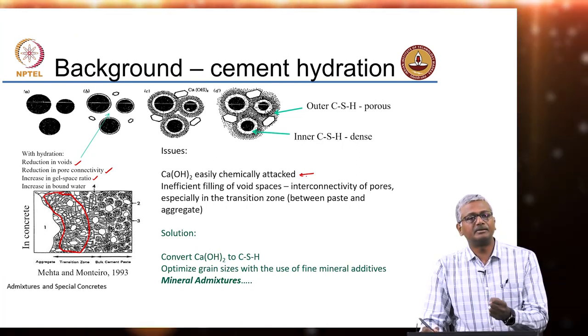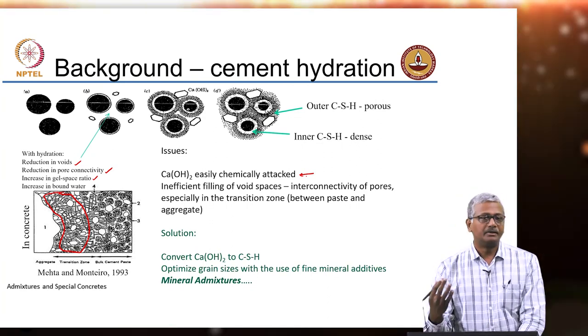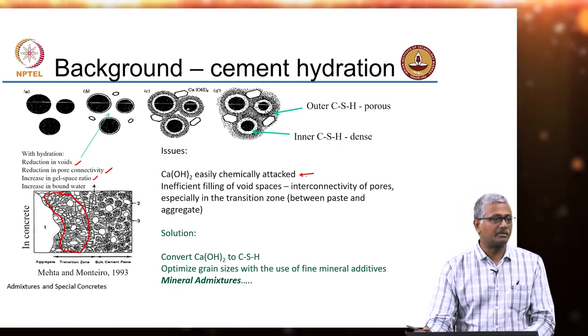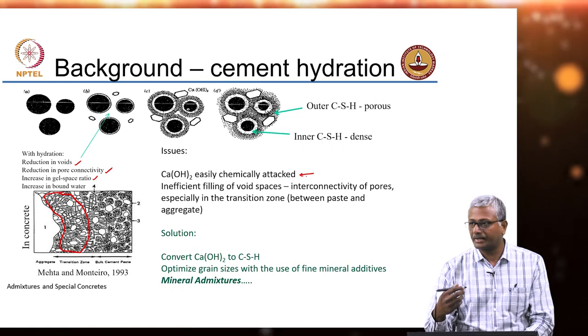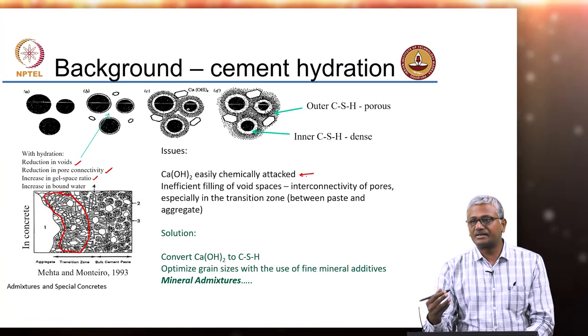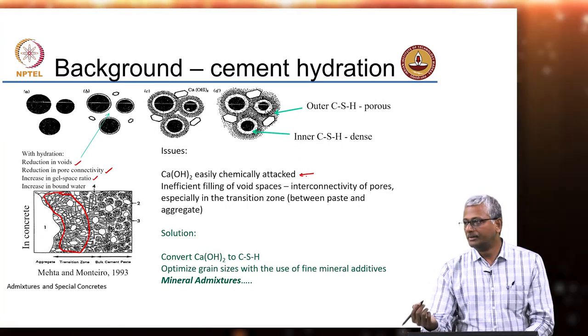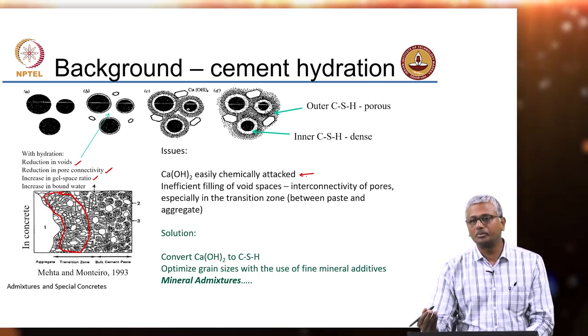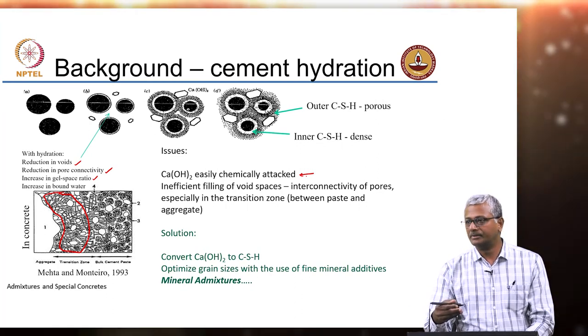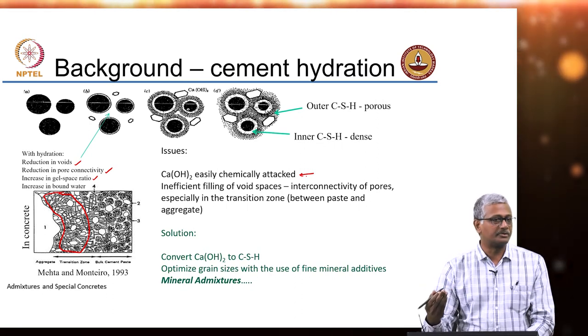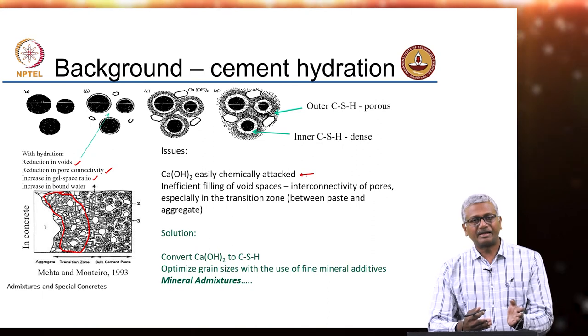In some instances, the quick reaction of calcium hydroxide in a chemical attack scenario is beneficial. For instance, in carbonation, attack on calcium hydroxide is beneficial because it creates a barrier of calcium carbonate. But in many other instances, the presence of calcium hydroxide is a deterrent. In sulphate attack or chloride attack, calcium hydroxide reacts to produce phases that are either soluble or weak. When chlorides attack concrete, chloride reacts with calcium hydroxide to produce calcium chloride, which is highly soluble, essentially increasing porosity. If sulphates attack calcium hydroxide, gypsum forms — calcium sulphate — which is much weaker than your cementitious phases, slowly reducing strength capacity.